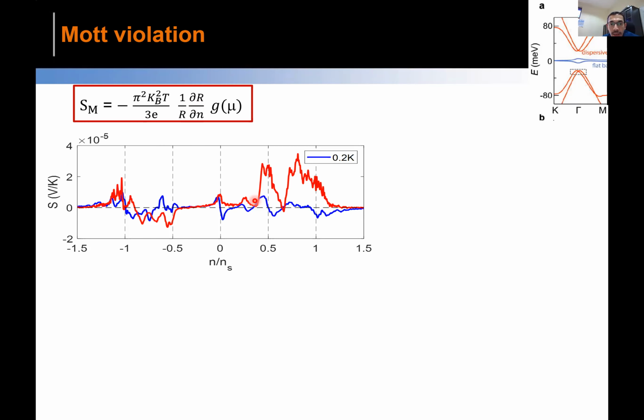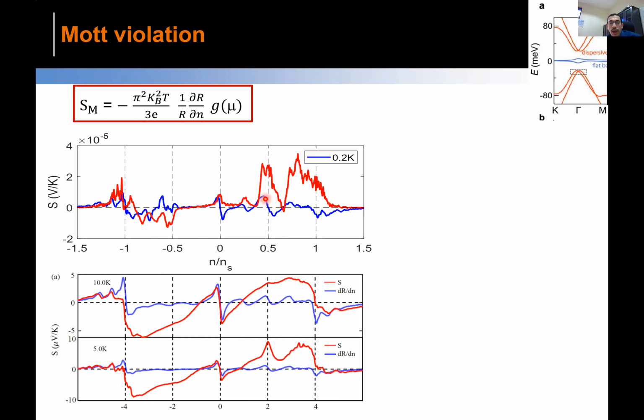So the blue line is your derivative of resistance, and the red is the measured thermopower. You see there is a huge difference between the Mott formula and the measurement. So you can immediately see the violation of the Mott formula in the system, and in fact that survives even up to 10 Kelvin. Again, for the blue derivative of resistance you have seen many crossings around the zero line, but for thermopower you see only one crossing. So clearly the Mott formula doesn't follow.